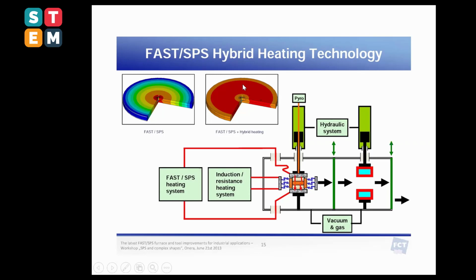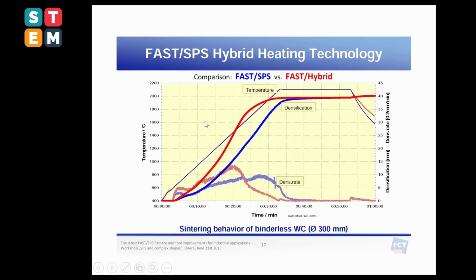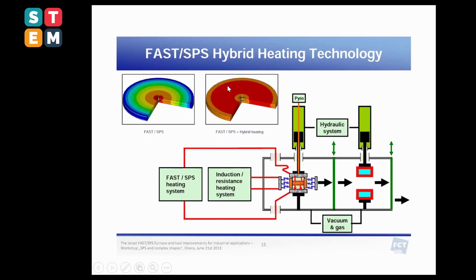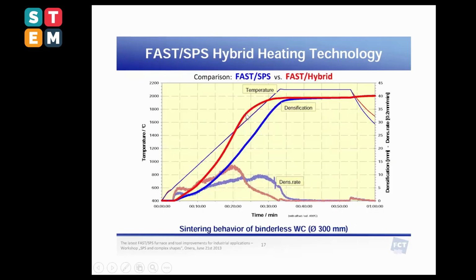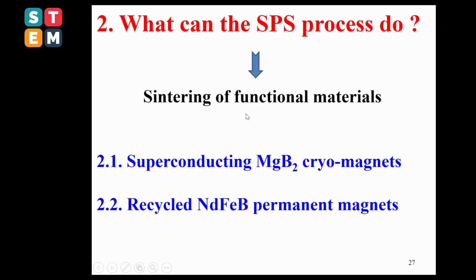And this was confirmed when you clearly observe here the shrinkage curve. This is the standard one, the blue one, and the hybrid system, where they were able to shift this. This is why they succeeded to produce this large sample by minimizing the thermal gradient.